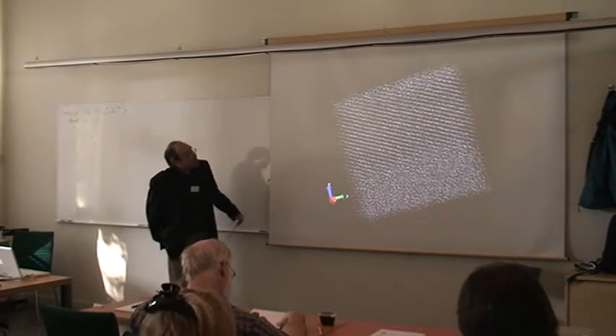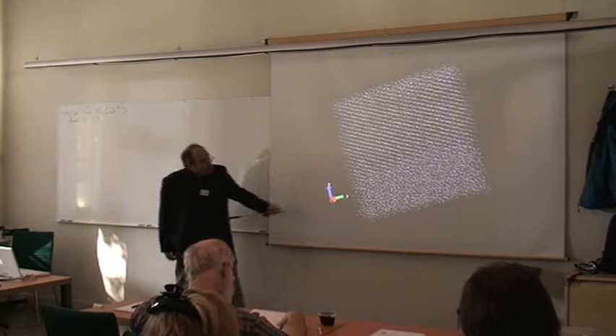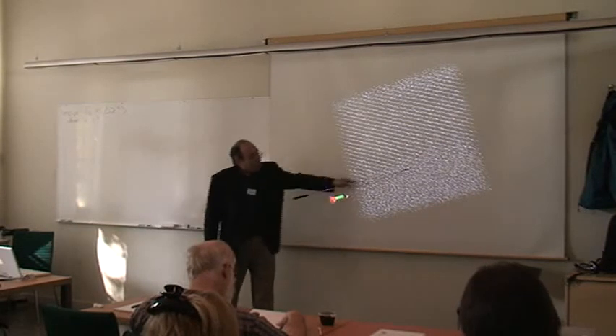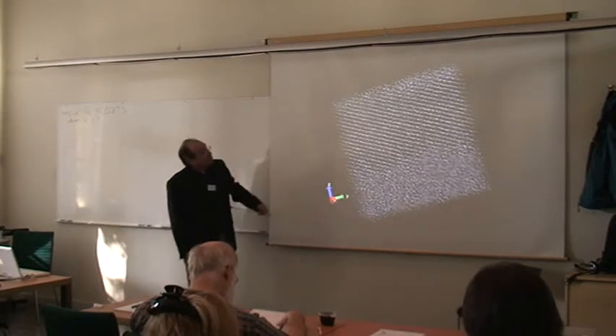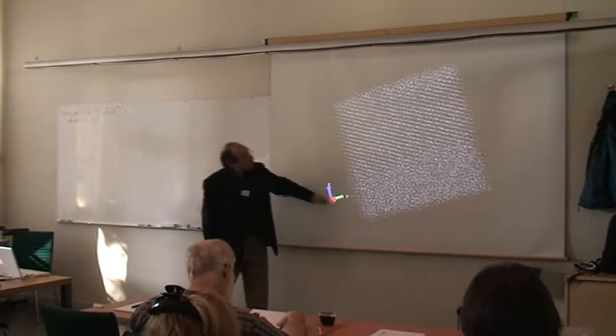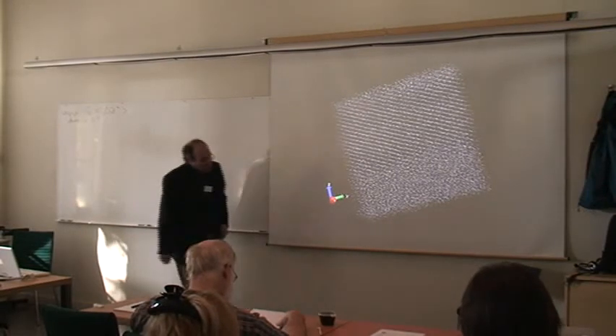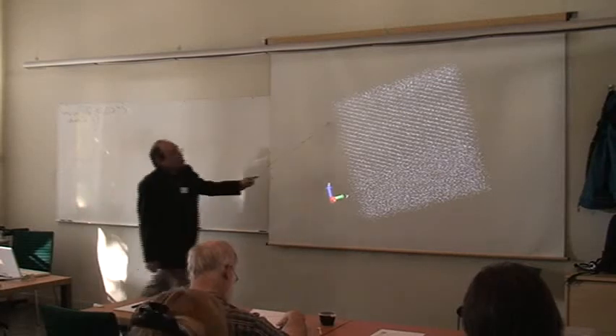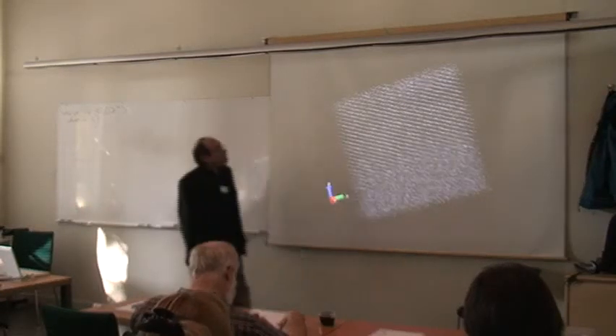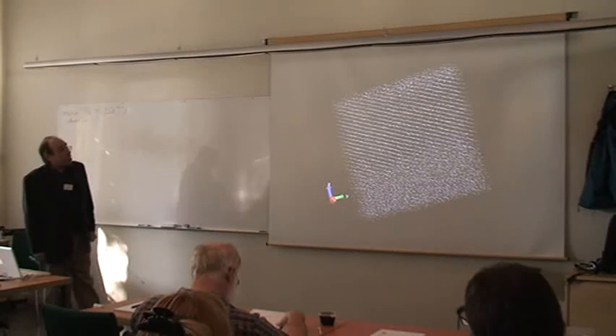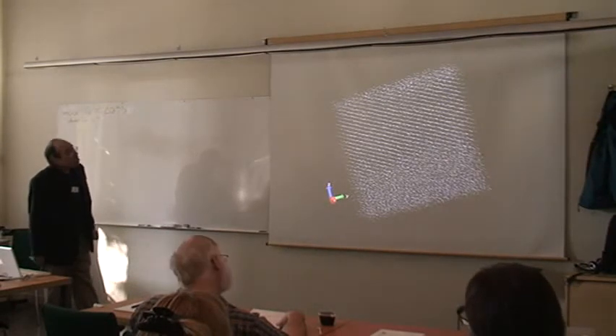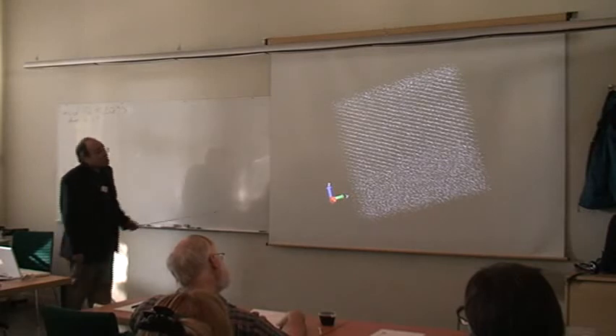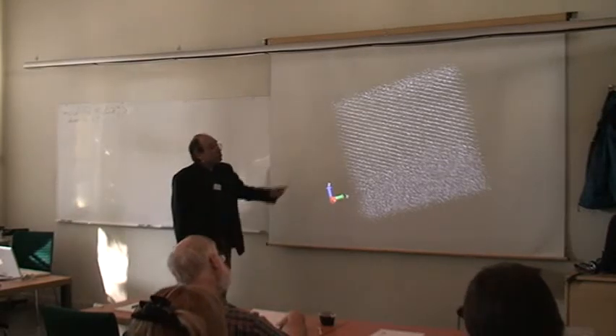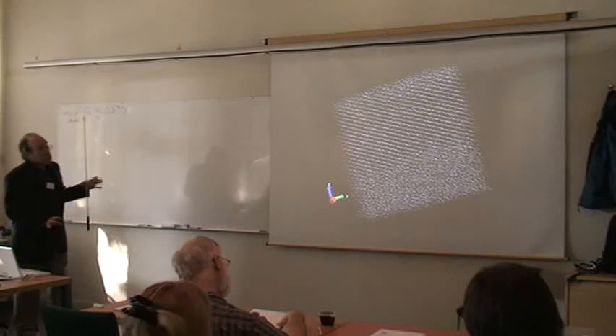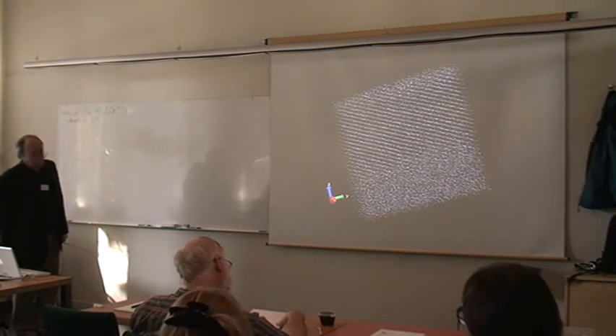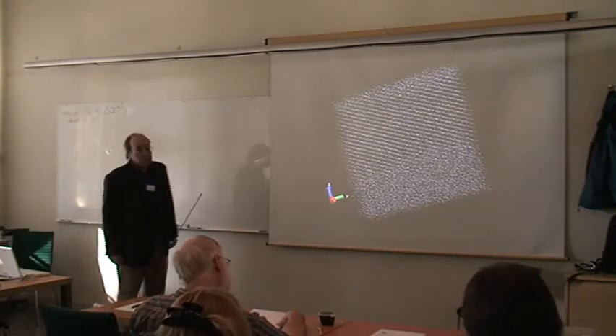We've carefully adjusted the temperature during the simulation so about half the material is liquid. This part down here is the liquid phase. There are periodic boundary conditions, so the liquid actually extends a little bit up to the top. Then you see you've got a solid here - those are the lattice planes. So even though you have all this complicated junk and impurities, it forms a nice regular crystal with very nice lattice planes. So the solid is not amorphous, it just has a bunch of impurities in it.